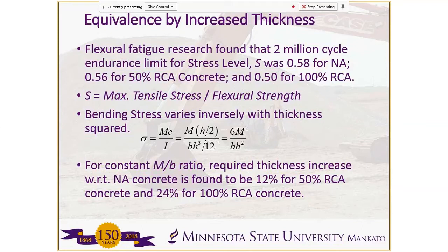So we found that for 50% RCA, you would need about a 12% increase in thickness. And for 100% RCA, that would be about a 24% increase in the pavement thickness to achieve similar fatigue lives.